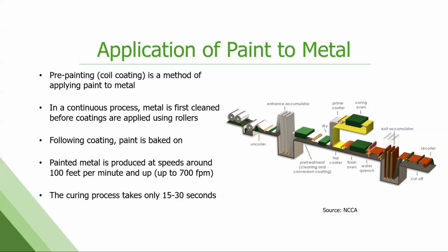Current technology, a whole car takes about 30 minutes to 2 hours to coat. We can coat enough metal in 15 minutes to make multiple buildings and roofs out of. So very different scale. It's also the thinnest coating applied in the industrial coatings world. We're applying this coating at about 0.0014 inches, which is thinner than paper, and expecting it to then go through the forming process and also hold up long-term on the outside of a building.